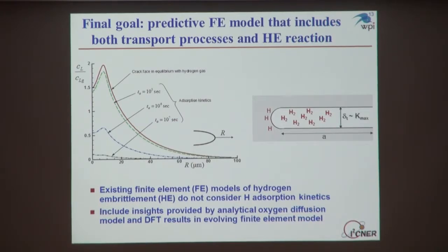And then, as I mentioned, Petros has the ultimate burden in this activity. He is tasked with developing a predictive finite element model that includes the physics of the hydrogen transport processes as well as the physics of the hydrogen material interactions leading to material degradation. And what he's already started to work on, and no one has ever accomplished this before, is to try to include the transport processes. And so this is just a plot showing how the concentration of hydrogen ahead of the crack tip will vary as a function of the time constant that represents the hydrogen reaction kinetics on the surface.